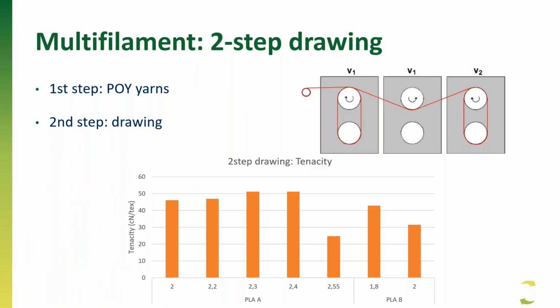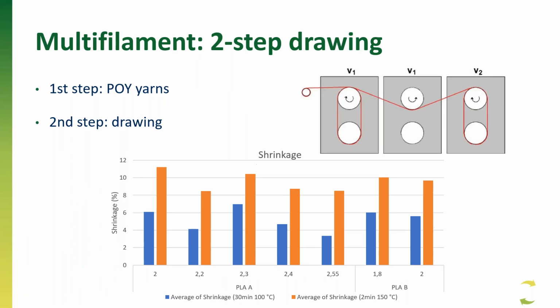So much higher strength, but also, and this is the main important one, the shrinkage that we want to lower from 20% to 10%, even ideally 5%. You can see here with some of them even reaching the 8% mark. We have done 2 different types of shrinkage method, but the orange one is the most important to look at, and there we can see that we almost reached the 8%. So going from 20% to the 8% mark, while also increasing the strength of the yarns. This is what was written also into this CWA.